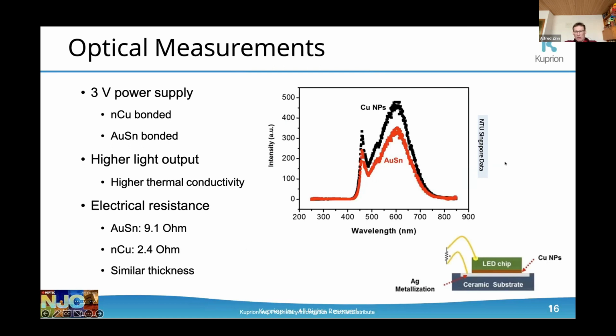This was done in collaboration with NTU in Singapore. We have been working with them for a long time and compared the same thing, a gold tin solder bonded LED and our copper nanoparticle bonded LED, and you see the much higher intensity under the same power settings. We also found that the electrical resistance is much lower, which you would expect for a pure copper system.